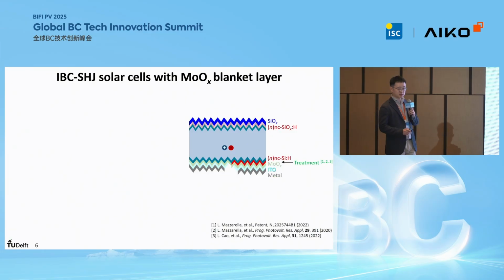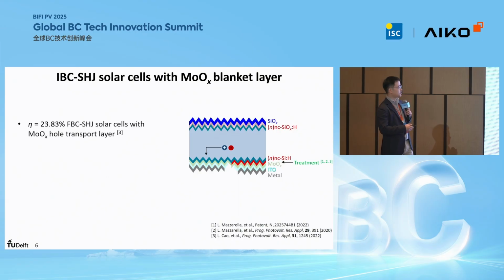In this type of IBC solar cell, the holes are collected through the typical dopant-free contact based on molybdenum oxide, a contact stack already evaluated in the front-back contacted design, having a certified efficiency of 23.83%. The electrons are collected through a contact stack that consists of an intrinsic layer, an N-type nanocrystalline silicon layer, and molybdenum oxide layers, and eventually the TCO and metal.